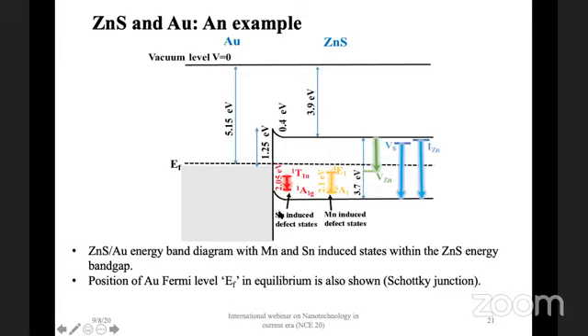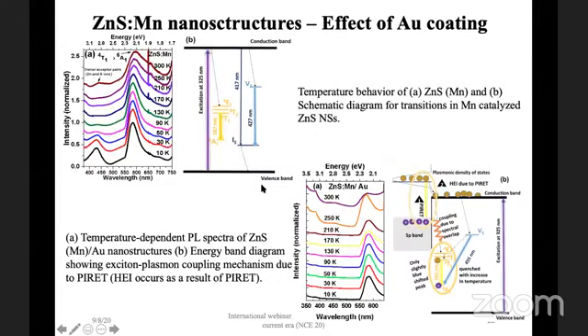Just to give an idea of what happens when we do excitation, the possibility is that we have transfer of carriers both ways. If we have hot electrons from the plasmons, they will come to the zinc sulfide side. And if we have carriers in zinc sulfide excited, they can go to the plasmon to excite the plasmon modes. Basically, this was a Schottky junction. So a Schottky junction, remember, is only a one-directional transport. It behaves like a diode. Now we did the temperature dependent study.